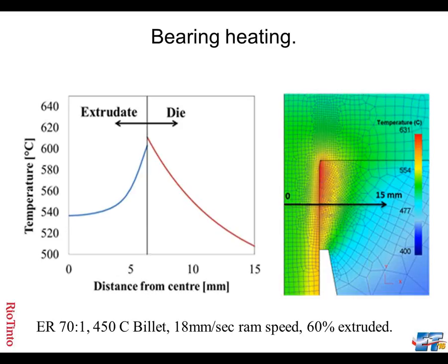And obviously, it explains if we're running extrusions at 630 Celsius, the dies are probably running at 640, 650, which is well above the tempering temperature of the steel. No wonder dies wear out. And this shows the gradient. The blue line on the left-hand side shows the gradient across the diameter.